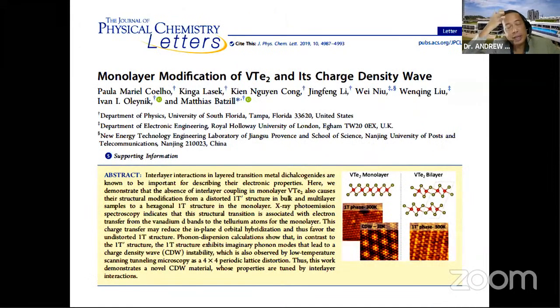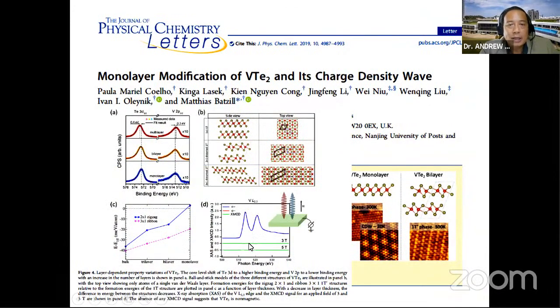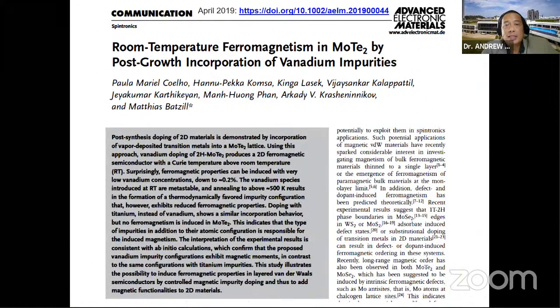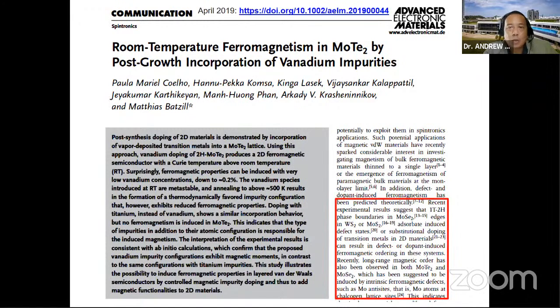And the interesting thing is that the same group that published in Nature Nanotechnology from Florida, the Batzill group, also worked on vanadium ditelluride. And this time they did XMCD. And again, they confirmed there's no dichroic signal. So they also found that this material is not intrinsically magnetic, which casts doubt on their earlier result on vanadium diselenide. And so this was in agreement with our data. But nevertheless, they also showed you can make other 2D non-magnetic TMDs like molybdenum ditelluride magnetic by incorporating, for example, vanadium impurities, because vanadium introduces magnetism. So they showed that in this case it's magnetic. So that confirms our postulate.